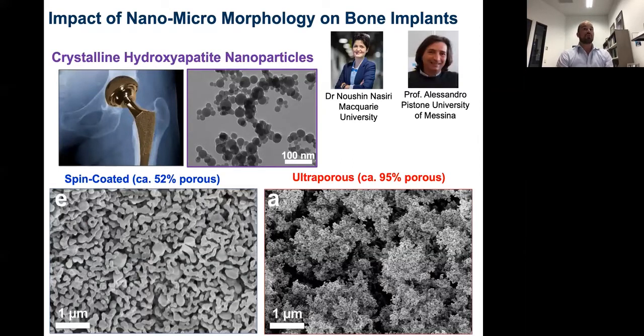So we do a lot of work in collaboration with several universities around the world on trying to improve bone implants. So if you imagine a knee or a hip implant, we're trying to improve the longevity of these implants. Currently, these titanium implants are either put into the body and they're not coated at all, so they're just textured titanium, or they're coated with an inorganic material known as hydroxyapatite. And the way they coat this is using a flame spray technique.